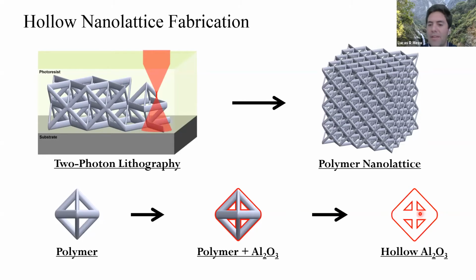Dimensionally, we can control the thickness of ALD effectively to the nano level, to the atomic level. We can get 10 or sub-5 nanometer thin films of aluminum oxide, which is effectively 15 to 30 atoms across. So we're really getting down to the scale where we're controlling the atomic organization of these structures.